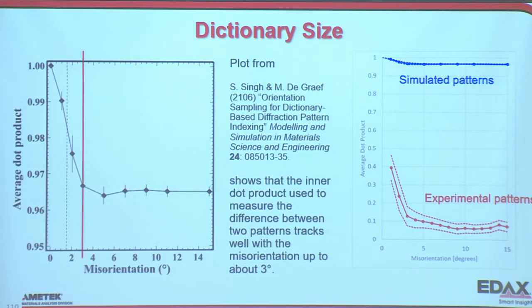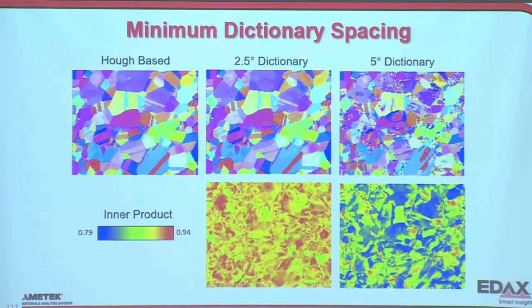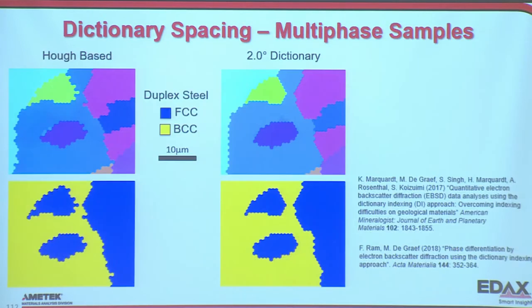But what that suggests is we've got to go out to around 3 degrees to get any kind of decent results. And if we do that, this is the Hough indexing, 2.5 degree dictionary, 5 degree dictionary. Clearly now it's not good enough. We don't have enough resolution to resolve the orientation, the patterns. So we've got to go to at least 2.5 degrees is my conclusion from that.